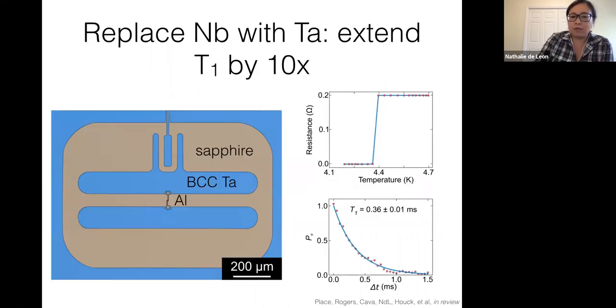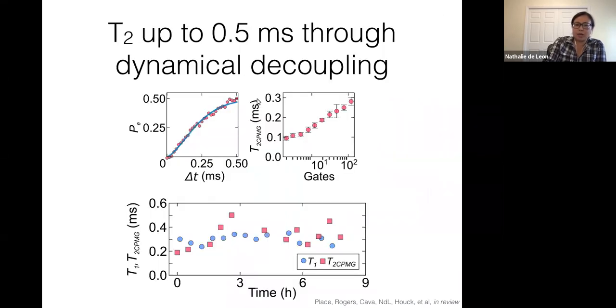Okay, so the end result of all of that materials work is that, compared to the niobium qubits that Andrew Houck's group was making, which were not as good as the absolute state of the art, we have been able to extend the T1 of these transmons by about a factor of 10. Our typical best now is a T1 of around 300 microseconds, which beats the previous record by a factor of a few. And this was just a very simple material change from niobium to tantalum. In addition, we can get T2s of around half a millisecond through dynamical decoupling.